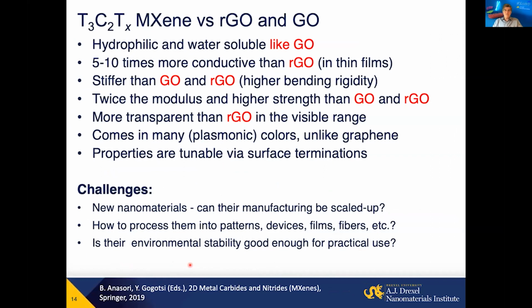So basically, if you compare it to graphene, you will see they are hydrophilic, water soluble, like graphene oxide. But unlike graphene oxide, they are conducting. Moreover, they're actually more conducting than reduced graphene oxide, which is used as a highly conducting additive, for example, in batteries that Professor Yang Horn was just talking about. It's also stiffer and stronger than both of those materials. More transparent at the same thickness, and also comes in a variety of different colors and properties that are tunable through surface termination and other things here.